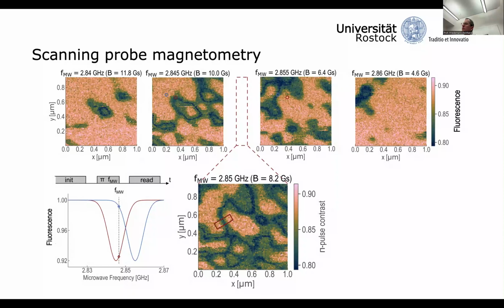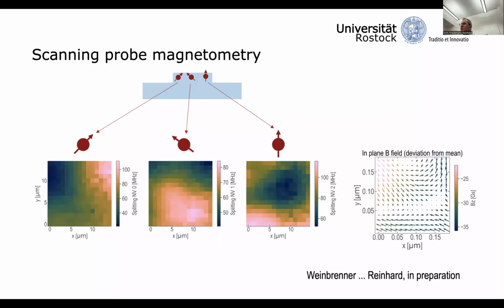So we are now able to actually do scanning probe magnetometry with such a setup, where we essentially look at a single NV center, do spectroscopy of its ground state spin transition with some specific frequency. Then whenever we hit some specific line of the magnetic field where the ground state spin transition becomes resonant with this, we get these dark fringes. And from these dark fringes, we can infer a full magnetic field picture. And importantly, we can do this on the same sample using different NV centers in this platform. Each of these NV centers will give us a different projection of the magnetic field, so we can even do full vector magnetometry with a single sensor.